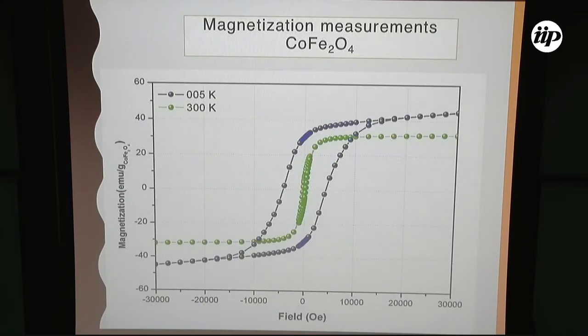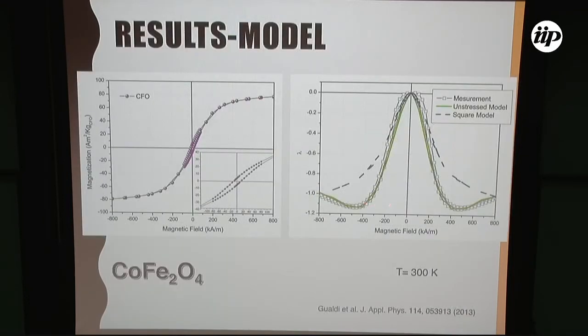When you apply this model, for example, to the magnetization as a function of applied magnetic field at 5K and 300K, it's possible to obtain the magnetostriction behavior directly from the magnetization curve. The square points are a direct measurement of the magnetostriction coefficient. The green is the application of this model, and the blue is the application of a square model at 5K.